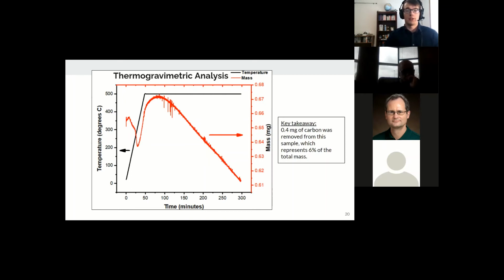The data from the oxidation process is displayed here. To read this chart, the temperature ramp is on the primary y-axis, and that's the data that's colored black. And so it's just a constant ramp at 10 degrees Celsius per minute up to 500 degrees, and then it's held steady. On the secondary y-axis is the mass of the sample, which you can see decreases steadily over time. And on the x-axis is time. So the sample started at about 0.65 milligrams, and it ended at just over 0.61 milligrams, meaning that the sample has approximately 6% excess carbon by mass.